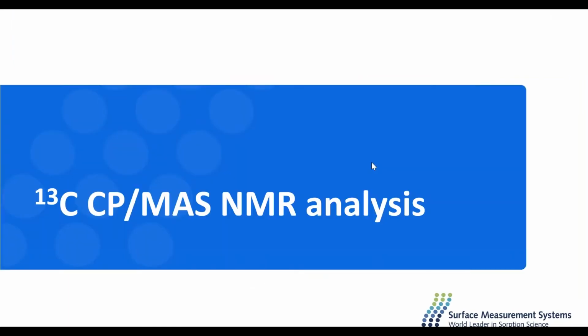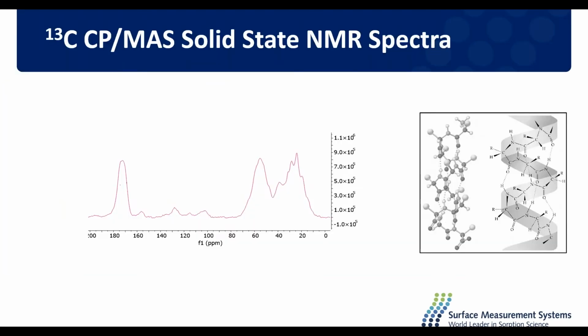So now that we had made these hair samples, it was time to characterise them, and we did this using solid state NMR. And here is a carbon-13 spectrum for untreated hair. This might be quite broad peaks in comparison to what many of you might be familiar with from solution state NMR. That's because in the solid state, we don't have that averaging motion from the molecules that you would find in liquid solutions, and this leads to quite significant line broadening. To counteract this, we spin our samples at very high frequencies to try and reduce those line broadening effects as much as possible. That's called magic angle spinning, and that's what we did here.